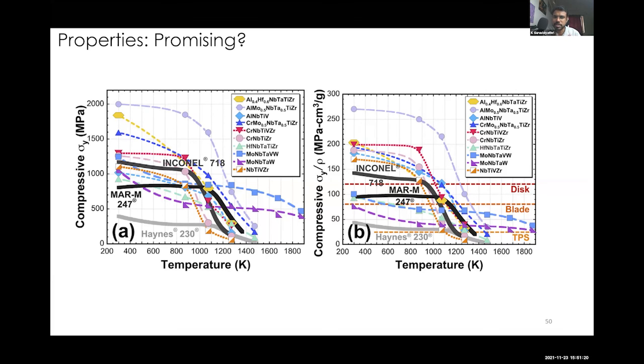No, there are restrictions coming from weight perspective. So we should not have high density. So people actually find out this compressive strength divided by density, that parameter, and draw this. Even in that, high entropy alloys are found to be much superior than nickel based superalloys. Okay, so this is promising.